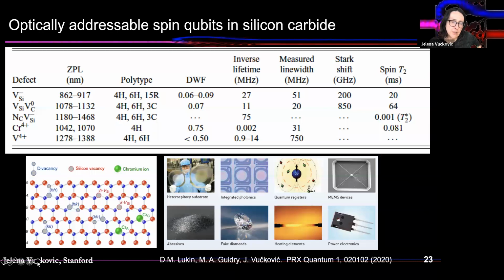The other set of qubits that we're interested in are related to impurities in silicon carbide. So these are again optically addressable spin qubits in silicon carbide. And there are many different color centers that people are studying here. My group in particular has looked into the silicon vacancy in silicon carbide in the 4H polytype. And again, silicon carbide has many different polytypes, which are different arrangements of silicon and carbon atoms. But we're interested in silicon vacancies, which are just missing silicon atoms in this particular polytype. And you see here that they have very nice properties and good coherence times that have been demonstrated.